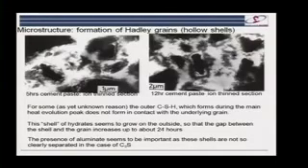And one of the things that's more and more complicated is the formation of what is often called Hadley grains or hollow shells. You can see in these transmission photographs, the dark stuff is the cement grains, and the bright stuff is where you've got holes, where the electrons go straight through. You can quite clearly see that this first product of CSH is not quite attached to the underlying grain. We now know that there is actually something in this space. It's just very, very low density. And this kind of feature persists, and a lot of these pores we look at are these little hollow shells.